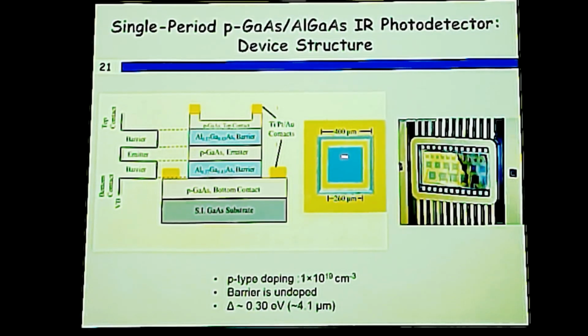Yes, and this top layer is partially etched to open it for optical illumination. Otherwise, most of the absorption will be in the top contact, so we get photoresponse mostly from the middle active layer. So this is partially etched. So the total thickness grown is like, yeah, here is just to show schematically. The total thickness in the design is 200 nanometer in this one, but it is partially etched, and after etching, there is about 20 nanometer or so left in that layer.